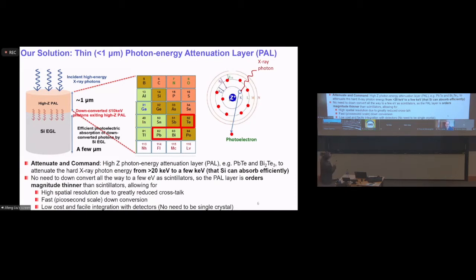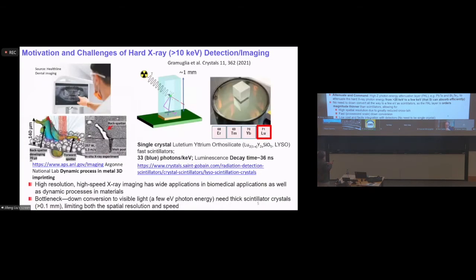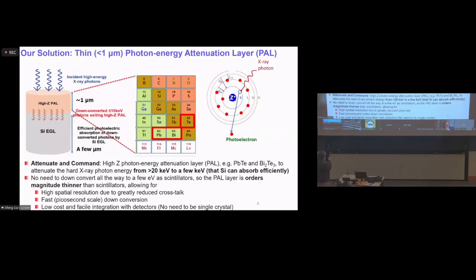So using this one, we are not converting the incident X-ray all the way down to visible photons. We're basically just decreasing that energy to a few kilo electron volts, such that silicon can absorb much more efficiently. Because we don't need to down-convert energy all the way down to a few electron volts in the visible regime. So this layer thickness is very thin compared to what you see in the previous slide. The previous slide is 1 millimeter. This one thickness is 1 micron. So essentially you can resolve that spatial resolution problem.